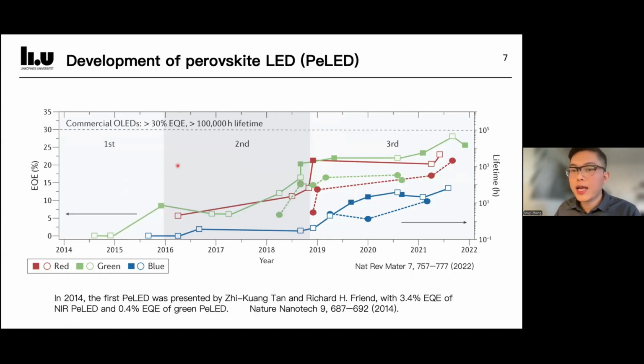And this graph shows how far PeLEDs have come in just 10 years. The axis is the year, starting from 2014 when the first PeLED was invented by Tan and Richard Friend. At that time, the EQE was only around 3.4% for near-infrared and just 0.4% for green LED. So it was a pretty humble beginning, but things changed very quickly. If we follow the curves, we can see how fast the field progressed. We have had three major development stages. The first focused on getting any emission. The second was about boosting EQE. And the third, which we are in now, is about pushing both EQE and the lifetime upward.